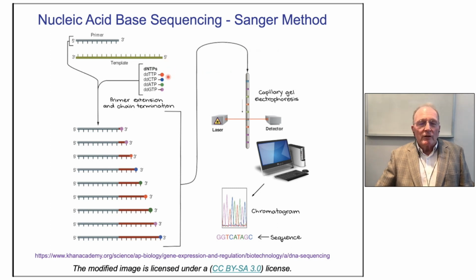And the idea was that for relatively short chains, you could get statistically the copy of the template according to the base incorporated, of all the bases present in the original template through this copying process. So you would end up with fragments, they'd stop growing, and each one would reflect the last base in the sequence down the chain. And then by gel electrophoresis, you could separate these. These all had fluorescent tags on them, so by fluorescence detection, one could identify the complementary base at the end of each of the growing chains.